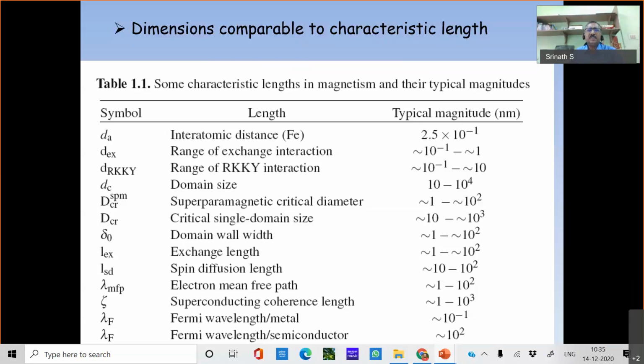For example, the exchange interaction, which is responsible for ferromagnetism or antiferromagnetism in a material, is of the order of 1 to 0.1 nanometers, the range of interaction. This is a very short-range interaction, wherein the electron wave functions in the neighborhood overlap either constructively or destructively, depending on whether J, the exchange integral, is positive or negative, giving rise to ferromagnetism or antiferromagnetism. And even the long-range RKKY interaction, which is also responsible for magnetism, is of the order of 0.1 to 10 nanometers. And the domain sizes are typically of the order of 10 to 1000 nanometers.